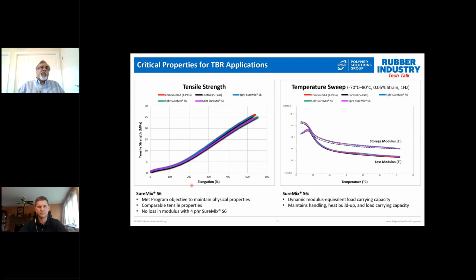So let's look at the physical properties. In this case, up to 4 PHR, we saw no change in the tensile curves. The tensile strength and the elongation to break, and especially the modulus, remained unchanged. We also looked at the dynamic properties, E prime and E double prime, and we found no change in those. So in other words, the properties were unaffected, but the processability was significantly improved, allowing the customer to eliminate 1 mixing pass.